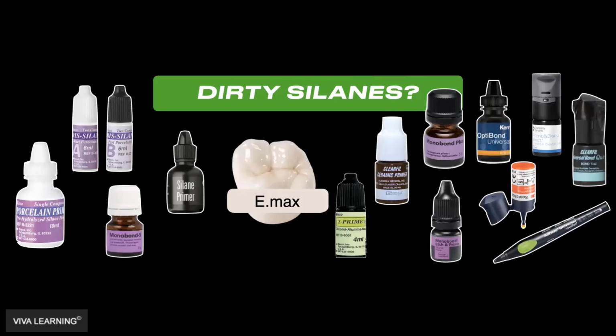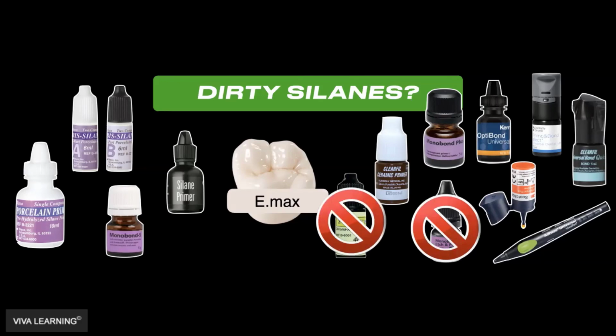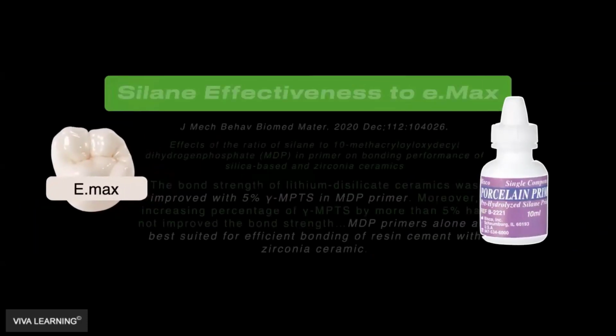It's funny because when Ivoclar went away from Monobond S, they did introduce Monobond Etch and Prime. And every study that's out there basically shows that Monobond Etch and Prime doesn't work nearly as well as hydrofluoric acid etch plus Monobond Plus. I mean, that should be pretty basic for all of us to understand, right? Hydrofluoric acid etching is obviously going to work better than an etchant that's inside of a silane. So don't use Monobond Etch and Prime, and don't use MDP on Emax. These other ones, your dirty silanes, they all do work. They really do. The universal bonding agents all have silane components in them, so they all can function as a silane. But the question is how much silane is in there.